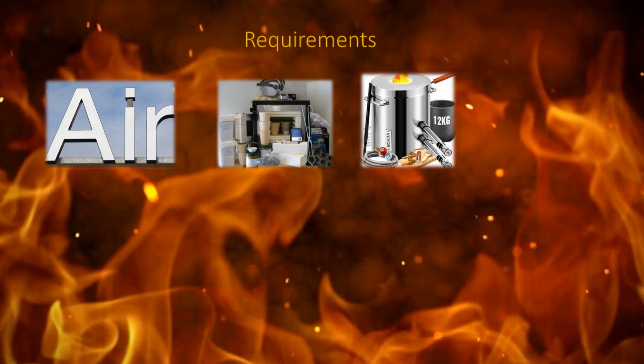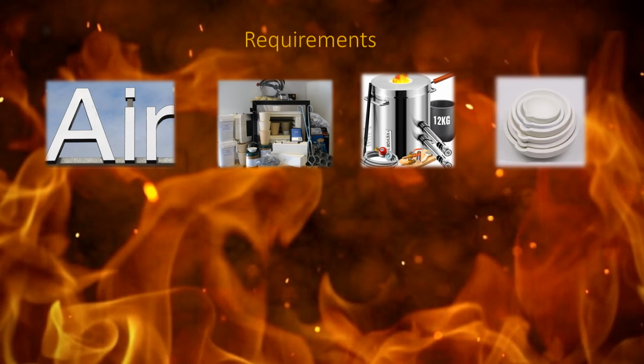The important thing about these furnaces is that the outside atmosphere must be allowed to enter the furnace in a controlled fashion. Also required is a method of temperature control. With a pot furnace, if it is not equipped with a pyrometer, you will need to use a handheld unit or use a color temperature chart and monitor the temperature manually and/or visually. A set of scorifying dishes are required. These shallow, circular, thick fireclay dishes range in size. Most commonly used range between 2 to 4 inches in diameter.